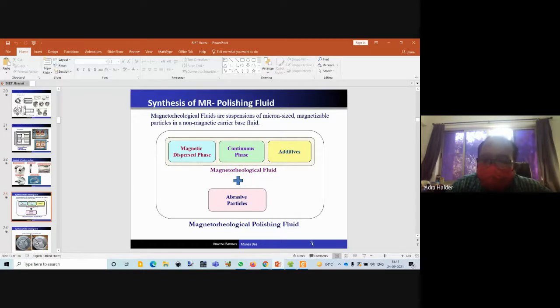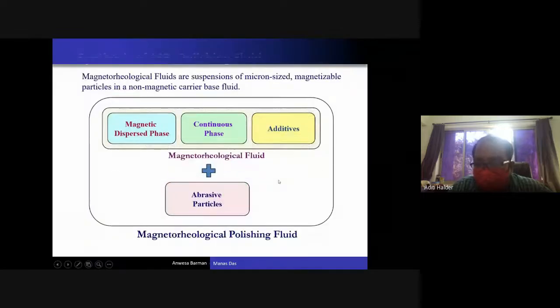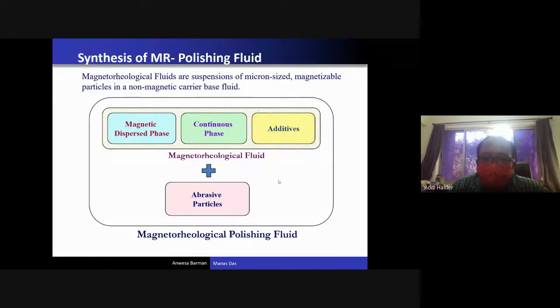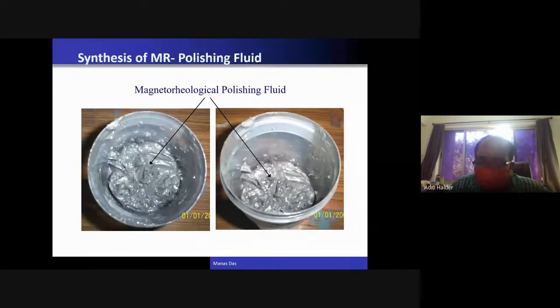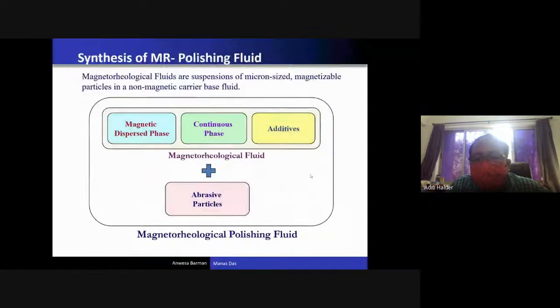So that's why some kinds of additives are used. These additives are oleic acid or glycerol, which you can use here. These additives are called surfactants. When you mix these surfactants along with this base media, they make a small layer over the surface of these magnetic particles. Because of the small layer generated over the entire surface of the iron particles, these magnetic particles cannot come close together. In that case, you can reduce or avoid the agglomeration problem.